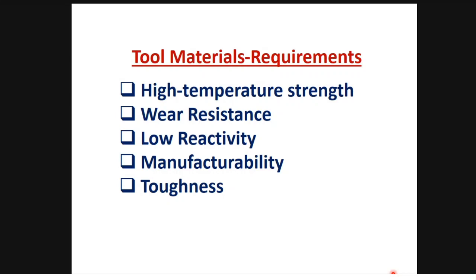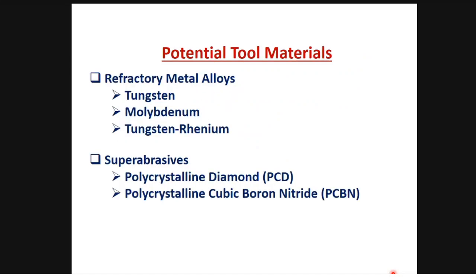Once the material satisfies all these requirements, only then can you use it for friction stir welding of high melting temperature material. You cannot use whatever material comes to mind, because some of the materials will fail on any one of these characteristics. If it fails, then the tool will be damaged, then the tool will break. So the potential tool materials are based on these characteristics. Basically, there are two groups of materials to be used.